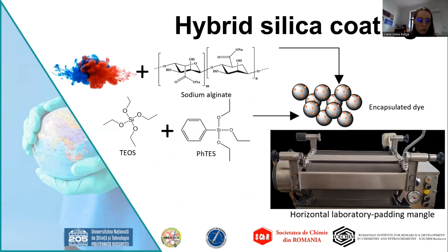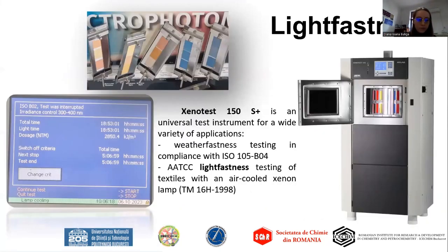Although many trials were performed, I chose to only depict the nanosol synthesis, where the first step was to put in contact the natural or the synthetic dye and the sodium alginate solution, followed by the capsule precursors, which were actually, in our case, TEOS and phenyl TES. The textile material was dyed using a horizontal laboratory padding mangle, as shown here. After drying the dyed fabric, the samples were subjected to a light fastness testing aided by the Xenotest 150S+. The light exposure was maintained for 180 minutes in total, with increments of 30 minutes each.